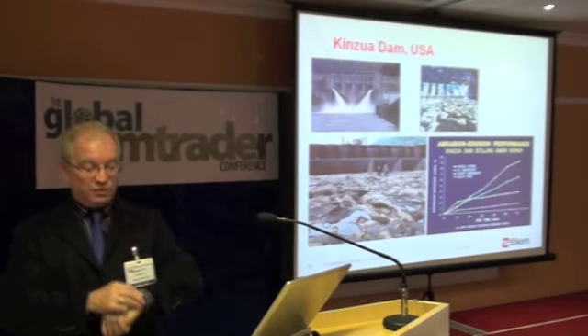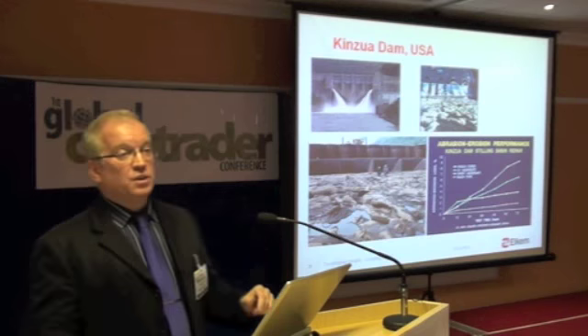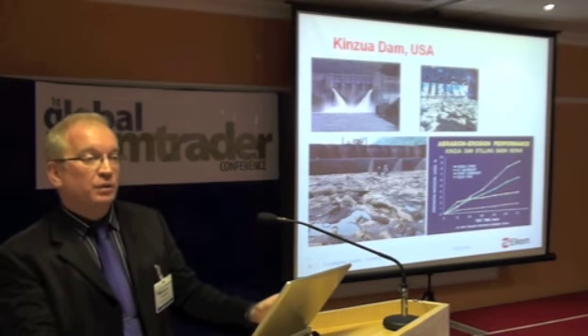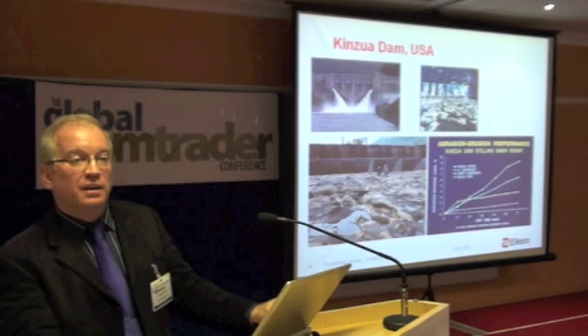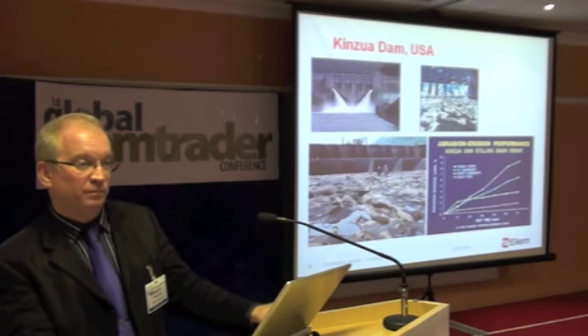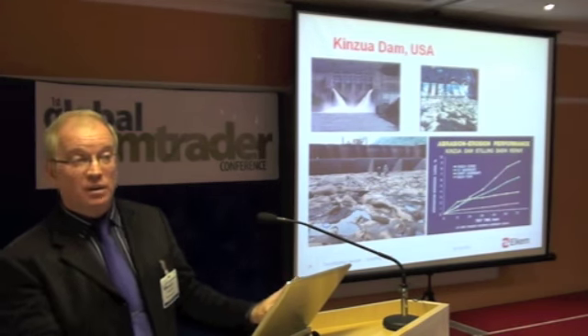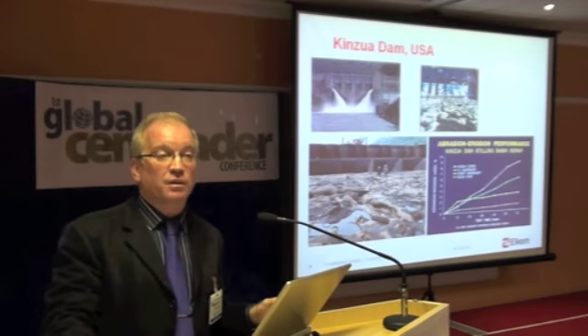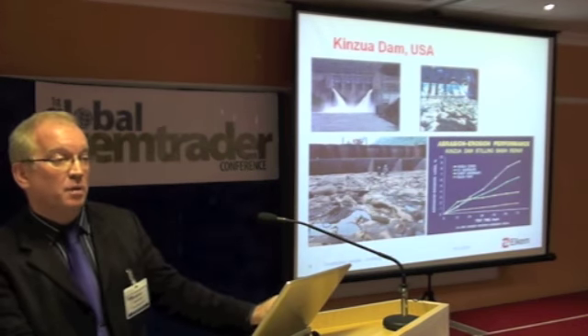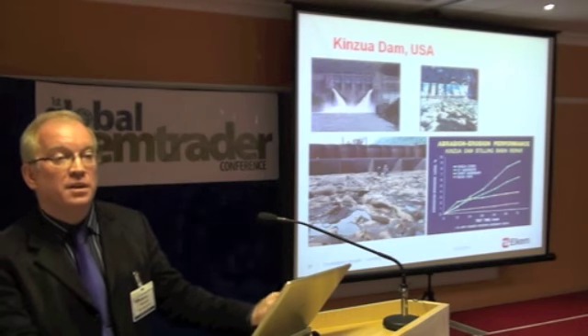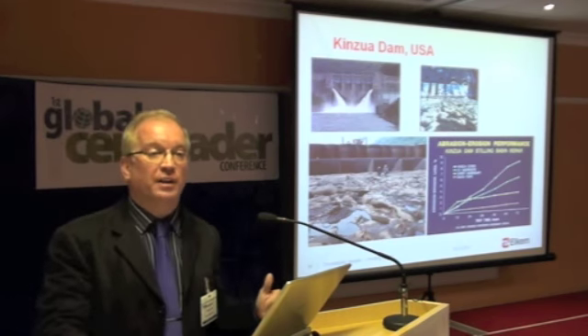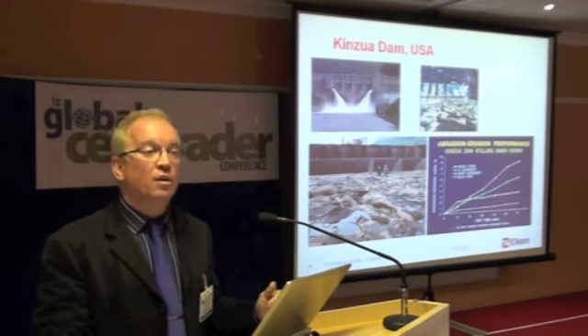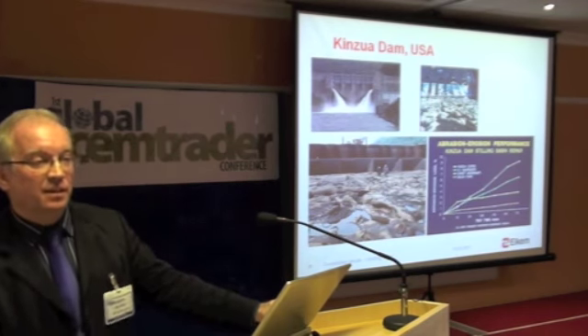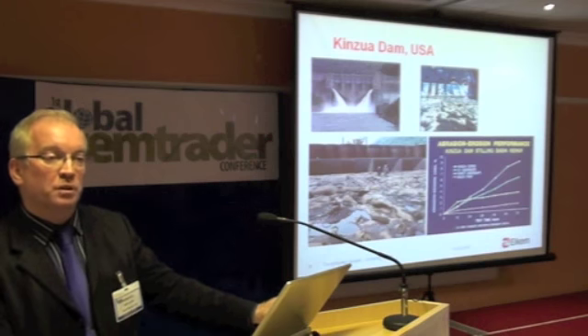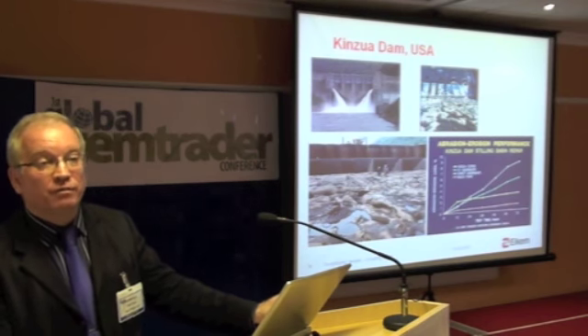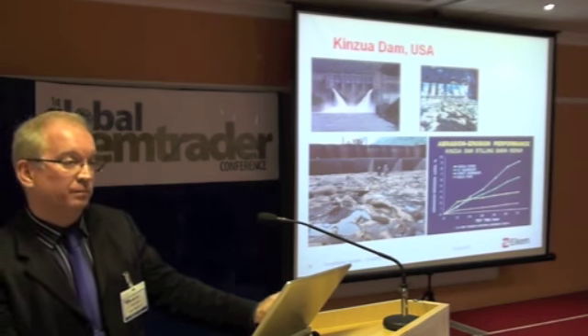Very quickly, to run through a few more. Kinzua Dam, durability. Built in 1967, repaired in 1974. With a high strength mix made of high cement content, strong aggregates that were shipped in, and steel fibres. Unfortunately, in 1983, this is what the Stilling Basin looked like after that. It had not only worn through the 3 feet, 1 metre of fresh concrete that had been put down in the repair, but 1 foot further into the original concrete.